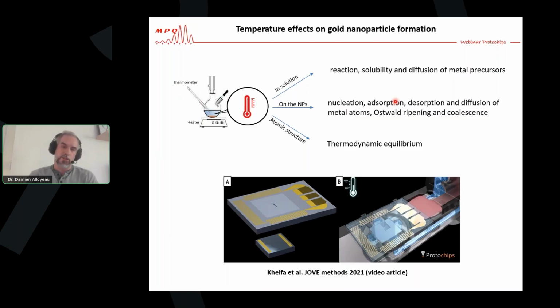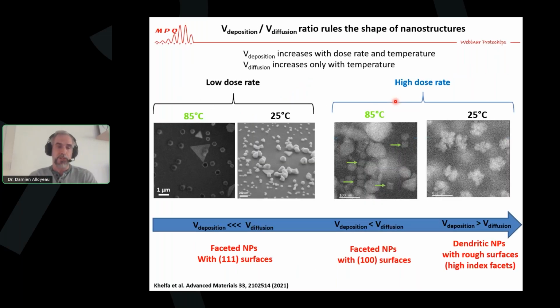And I show you only one part of the result, just about the shape, what's going on when you play with the temperature. What is interesting with this experiment is that the deposition speed increases with both the dose rate and the temperature, but the diffusion of metal atoms at the surface only increases with temperature. So now, by playing with both dose rate and temperature, we have a way to visualize the effect of this competition between deposition rate and diffusion rate. And the result is shown here.